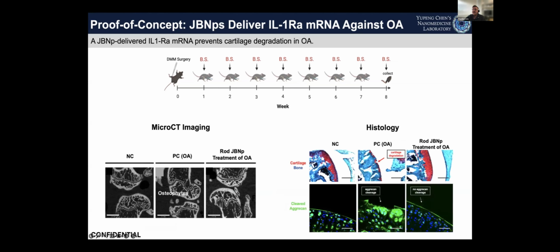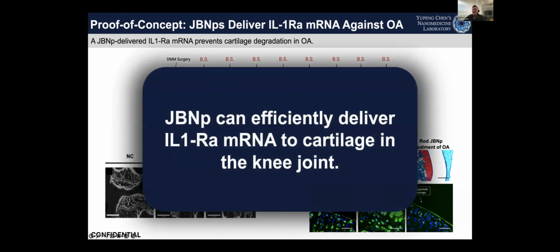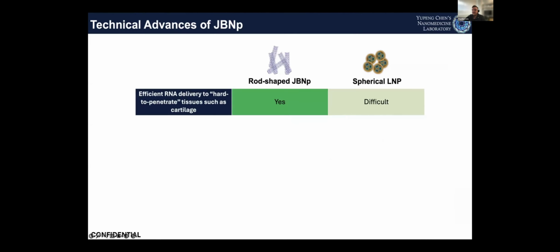On histology, we essentially saw the same thing. On the top, the treatment group preserved a thicker and healthier cartilage layer than the non-treated group. Then on cleaved aggrecan staining, the same is true again, where we see that the JBNP treatment group showed no signs of cartilage degradation, but the untreated group showed extensive cartilage degradation. These results in combination with the behavioral study data tell us that the JBNP delivered a viable copy of the interleukin-1 receptor agonist mRNA to chondrocytes in the knee joint, and they were able to produce good copies of the therapeutic protein. This means that JBNP can be used to deliver a bioactive mRNA to cartilage in the knee joint.